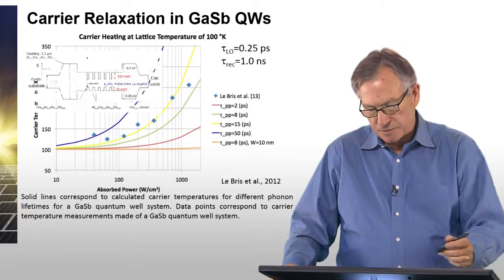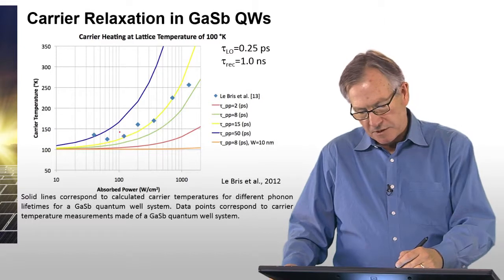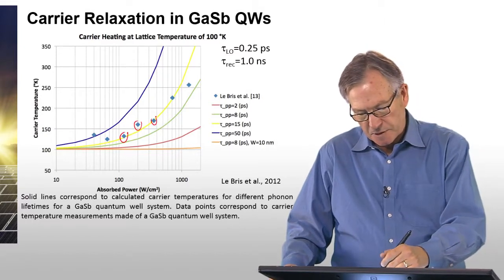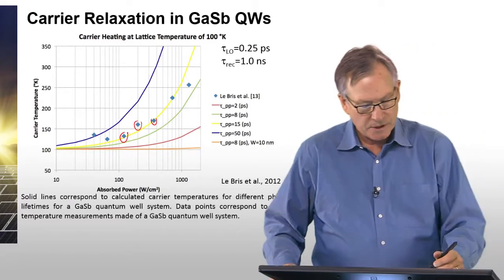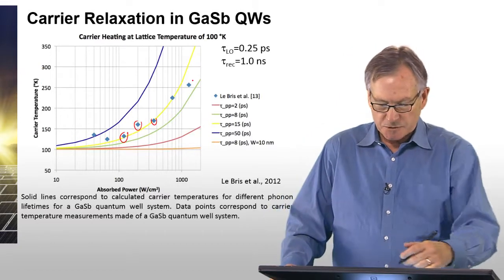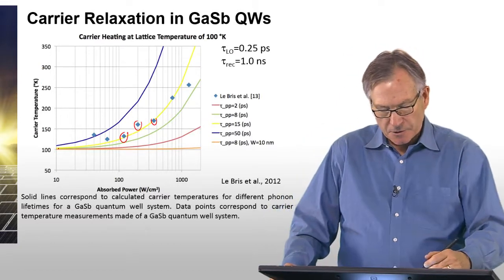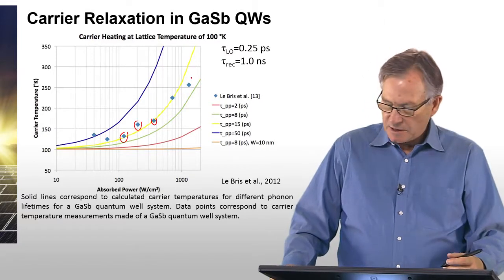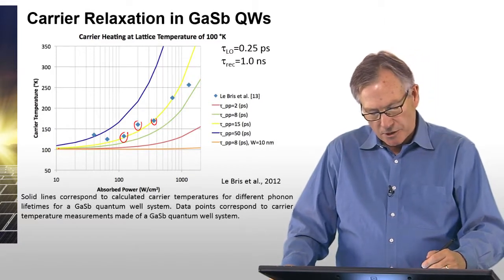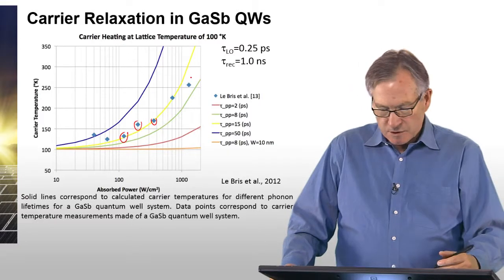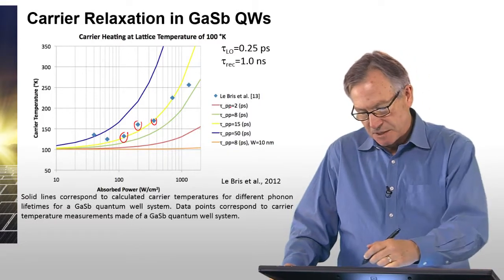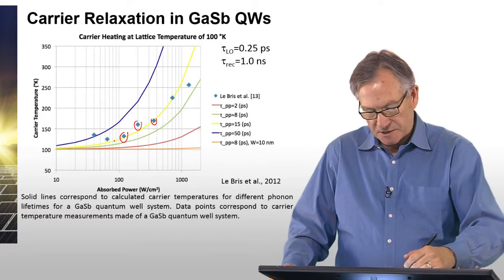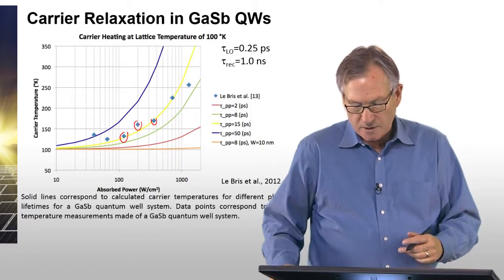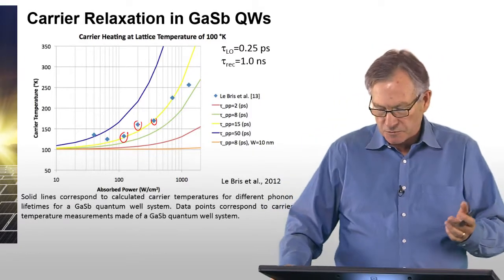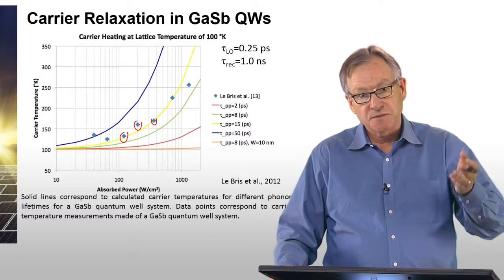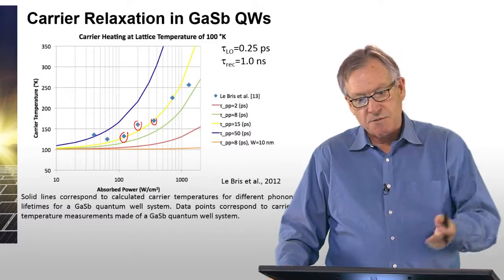So this was the structure, and what's shown here by the diamonds, these are the experimental points. So as the absorbed power goes up, the measured carrier temperature spectroscopically increases. So they start at 100 degrees, they get up to about 250 degrees. And this has then been modeled by our group, which shows that assuming different phonon relaxation times, going from 2 picoseconds to 50 picoseconds, you get a good fit with a phonon lifetime of 15 picoseconds, which is not unreasonable to be able to achieve in, say, a layered structure system.